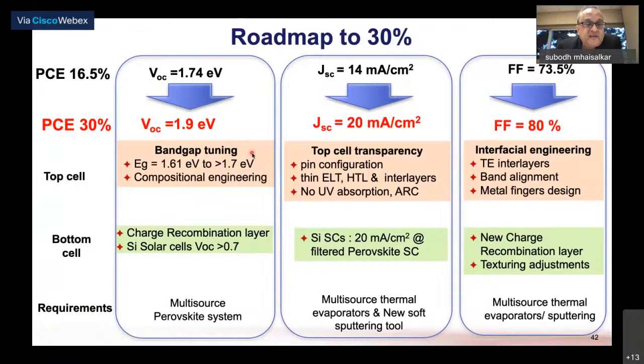What is essential there is new perovskite materials that will give you a band gap of about 1.7. What is also essential is to work on the silicon bottom cell and to push its VOC to more than 0.7 volts, and to look at different recombination layers. The other aspect to work on is to push the JSC to 20 milliamps per centimeter square, and this needs to be done by changing to the PIN configuration, thinning the individual layers, making sure that you really have no parasitic absorption in the other layers, and also working on higher performance of silicon, especially in the IR range. What would be needed is silicon bottom cells that can give you a JSC of more than 20.